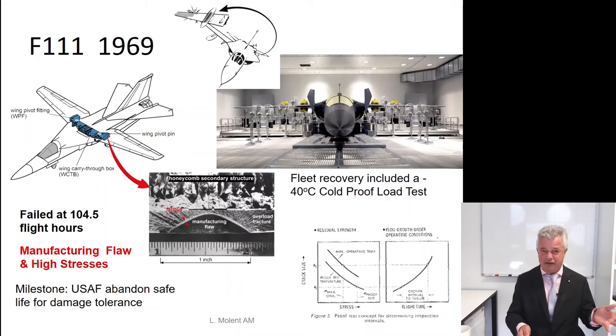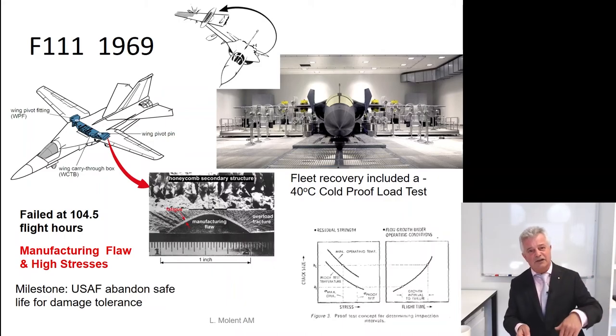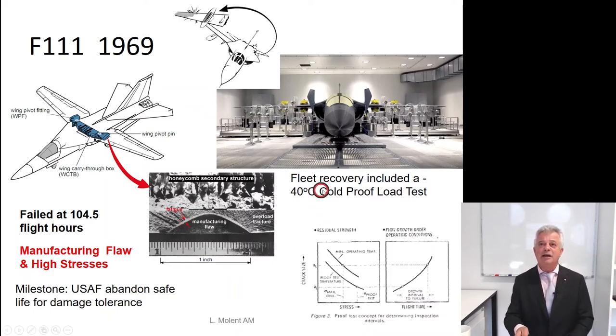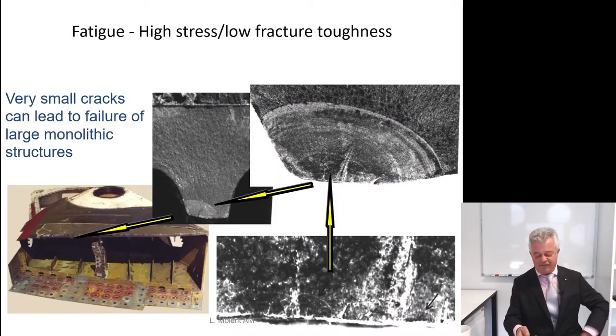The USAF abandoned the safe life process for the damage tolerance process, and to recover the fleet of F-111s, they would periodically be put in a chamber, there is the chamber, cooled down to minus 40 degrees, and then maximum loads were applied. Excellent. If it didn't fail in there, which many did, it was safe to fly for another 2,000 hours when it went back into the box. Expensive, but the only way to ensure safety. Yes, the RAAF lost several.